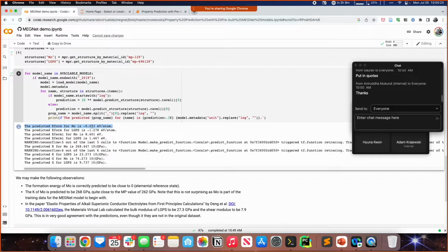Okay? So everything else, you just need to run the cells, right? So now I'm going to talk a little bit about the results, okay? So you see that the predicted formation energy for molybdenum is negative 0.003 eV per atom. So molybdenum is an elemental reference state, right? So for elemental reference states, usually we peg the formation energy of those elemental reference states as 0, and the model correctly predicts the formation energy of molybdenum to be close to 0, right?